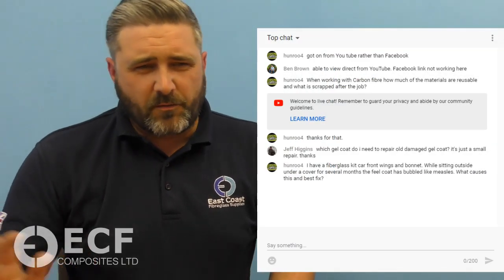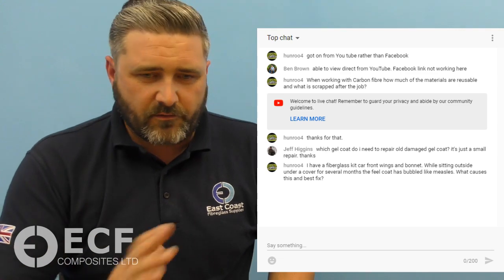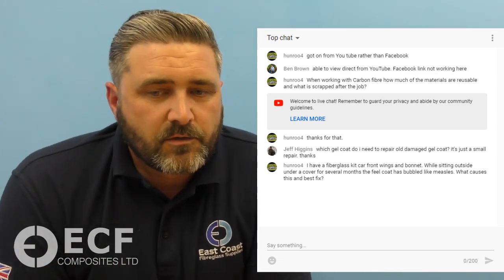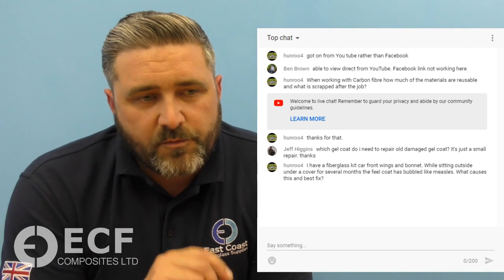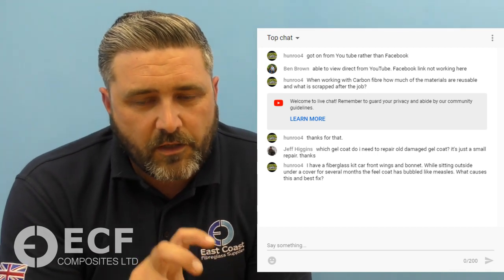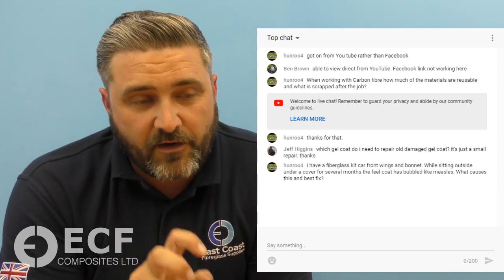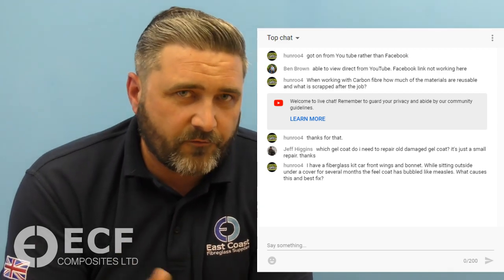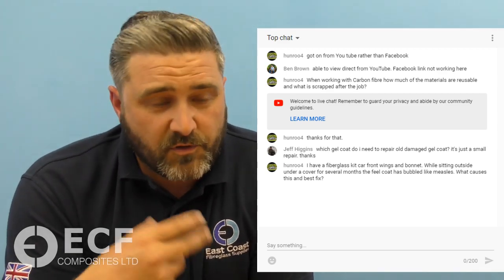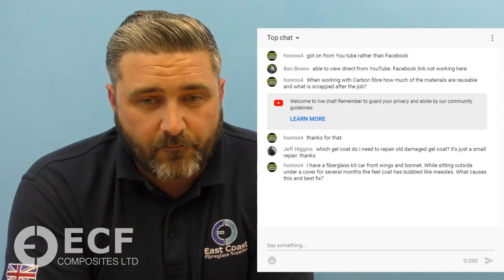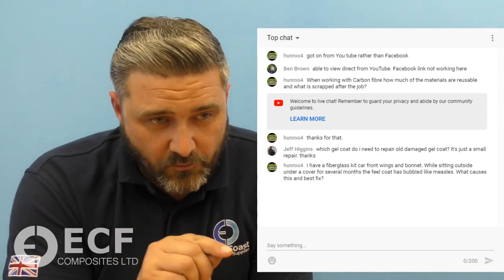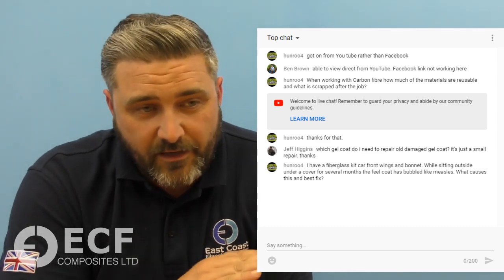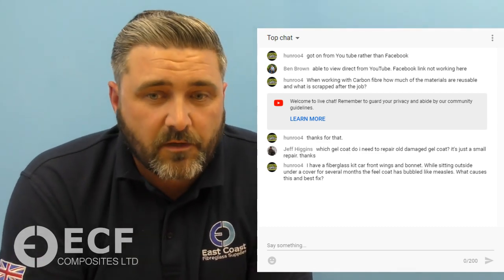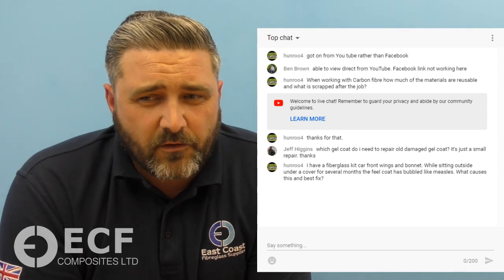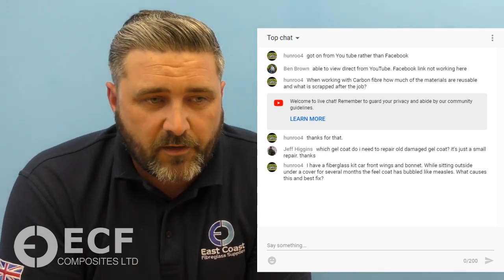However, if it's a larger repair, you don't want to be going through loads of sheets of wet and dry, gumming up all the time with the tackiness. So then you would use a flow coat. But always bear in mind, flow coat, you can only apply that as your final last coat. You can't effectively put a flow coat on top of a flow coat because you won't get that chemical bond due to the wax. So if you want to build up some height, you can gel coat a few layers, then finish with a flow coat, and then cut it back if you wanted to. But there's no real need for a flow coat if it's a very small repair.